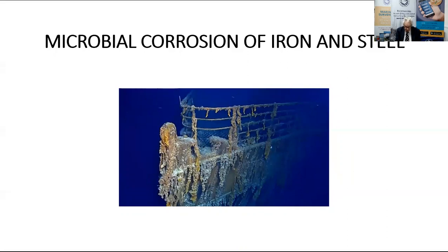Sulfate-reducing bacteria, or SRB, which produce hydrogen sulfide from dissolved sulfates in anaerobic conditions. The bottom of the pit that results is black. I have a picture to show you later on. Wet hydrogen sulfide is reported to corrode mild steel at rates that can exceed 2.5 millimeters per year, but it doesn't corrode aluminium alloy to the same extent.